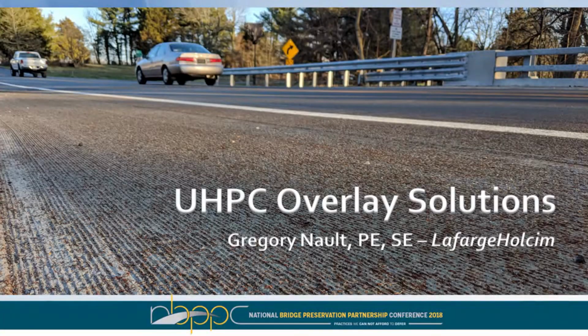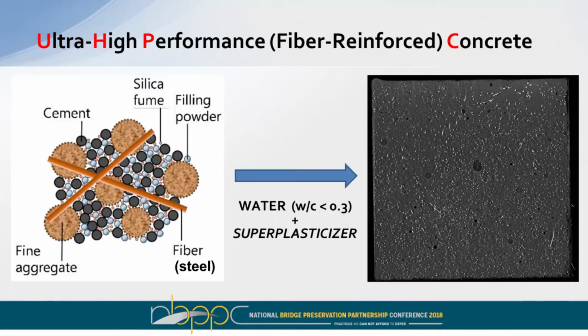I'm going to build on what Zach started talking about as far as UHPC goes. But basically, it's a concrete material. Cement, sand, silica fume. No coarse aggregate in this technology. It's all very fine particulate. You add a fairly low water to cement ratio, generally less than 0.3, a heavy amount of superplasticizer to keep it flowable, and then once it hardens and you cut it, a heavy dose of fibers as well.